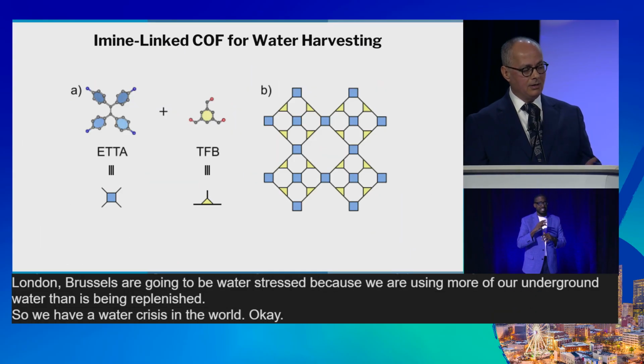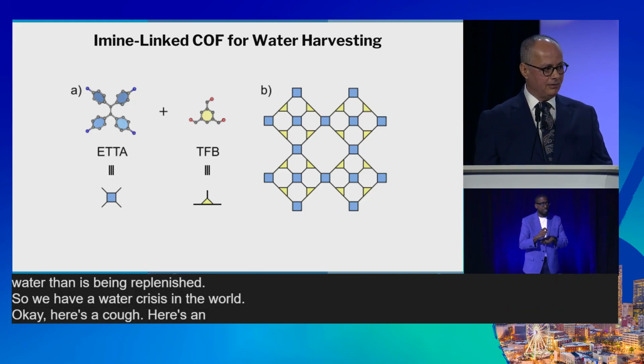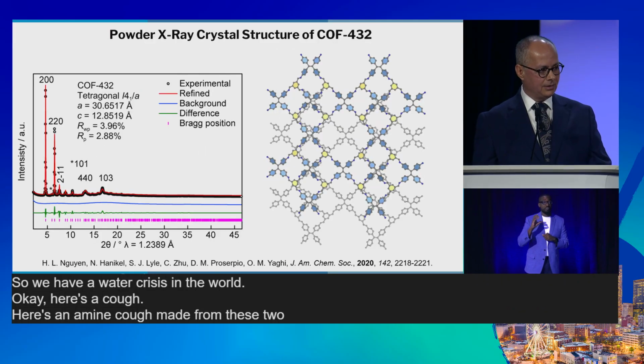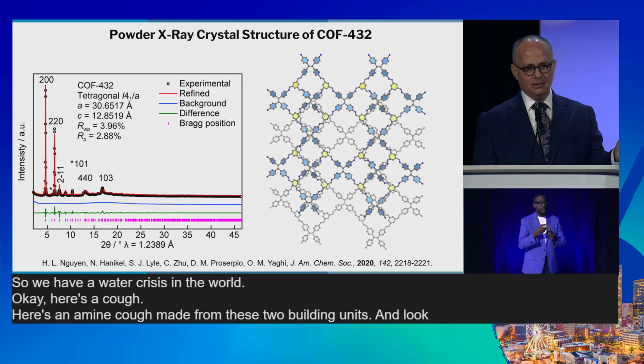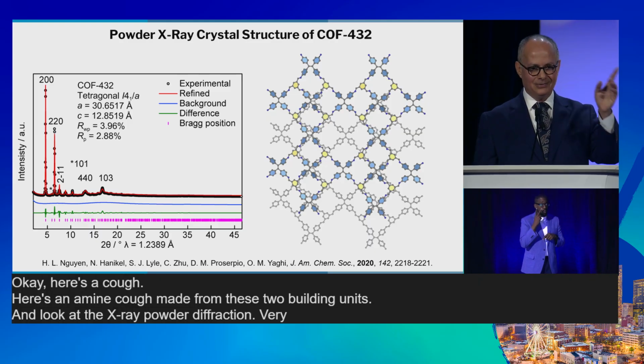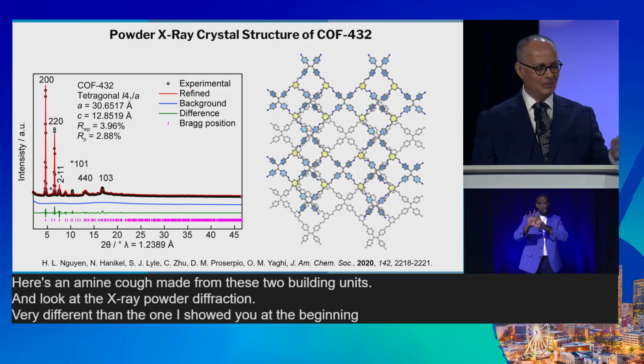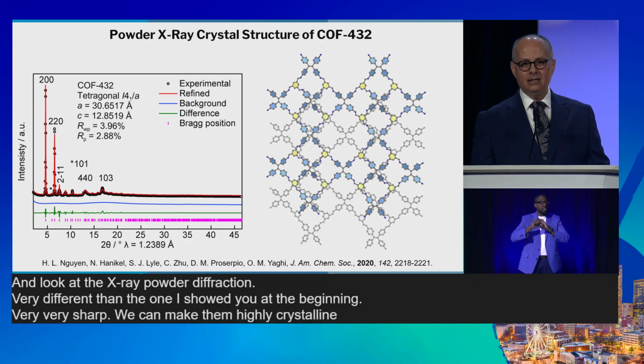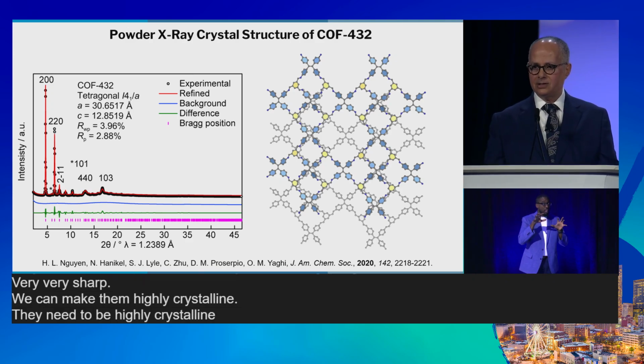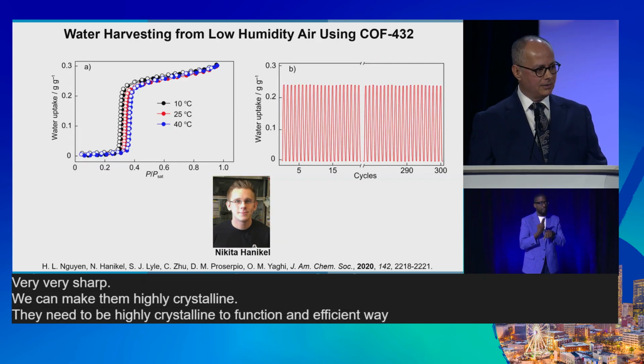Okay, here's a COF. Here's an imine COF made from these two building units. And look at the X-ray powder diffraction, very different than the one I showed you at the beginning. Very, very sharp. We can make them highly crystalline. They need to be highly crystalline to function in an efficient way for water harvesting. And here's the water harvesting.